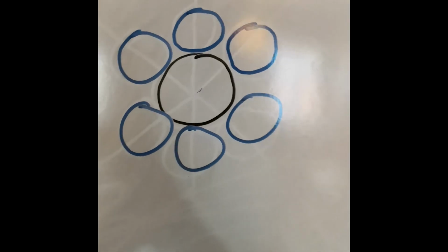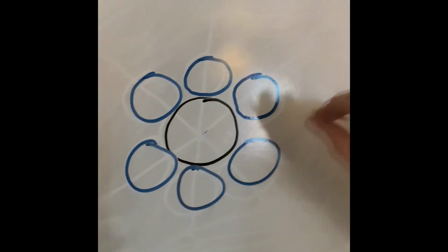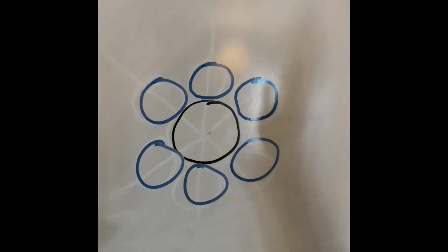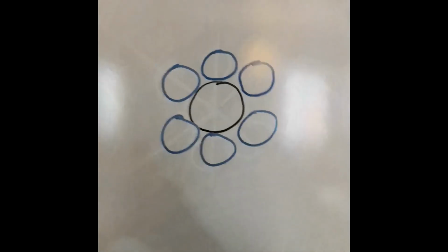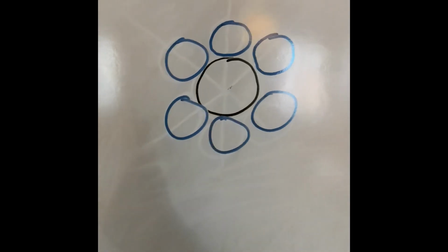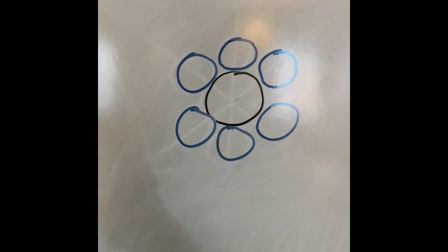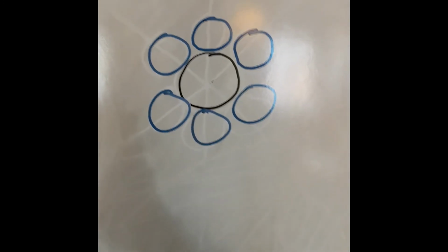When we have a substitutional impurity atom, that is represented in the bubble raft model as a bubble of a larger size, this can interfere with the movement of dislocations, as the dislocations will get to this point and the extra half plane won't be able to migrate or climb across that dislocation due to the high energy barrier associated with that movement. So what we see in the bubble raft model is edge dislocations coming and getting locked around this substitutional impurity, i.e. a larger bubble.